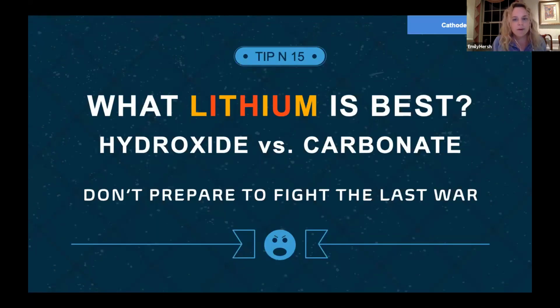So going back to this kind of battle, you'll see a lot of news and media talking about what lithium is best, whether we want lithium carbonate or lithium hydroxide, or if a project should produce lithium carbonate or lithium hydroxide. And quite honestly, it depends. The advice that I give is don't prepare to fight the last war. Just because right now, high nickel cathodes are helping solve range anxiety to get electric vehicles to performance parity with ICE vehicles, and just because you're seeing the move away from cobalt push automakers to want a higher nickel cathode, that doesn't mean that trend is going to continue.